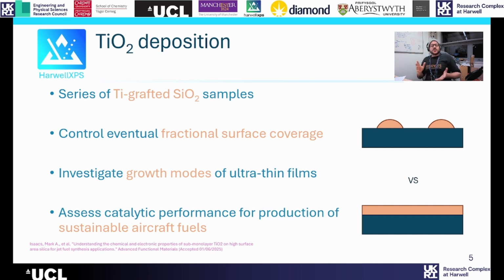The titanium alkoxides were added to the silica support in stoichiometric amounts relative to the amount of silanols on the surface in order to produce fractional surface coverages from 0.2 to 1 of a completed monolayer. And then our challenge was to investigate the structures formed, identify what chemistries were being produced on these surfaces, and correlate these with the catalytic assaying of these materials for the double aldol condensation of furfural and cyclopentanone.